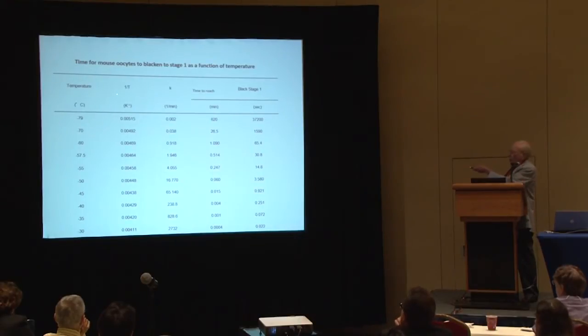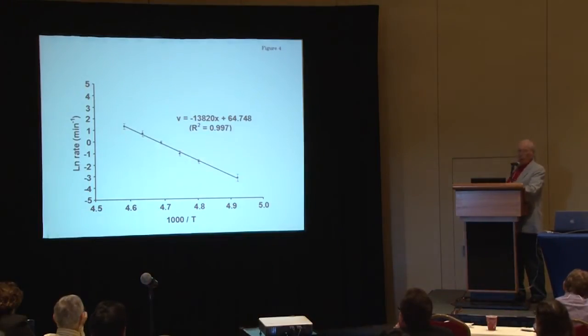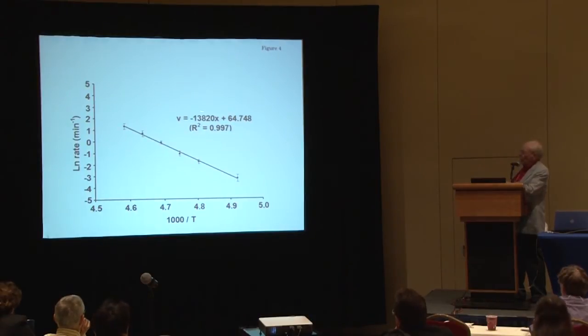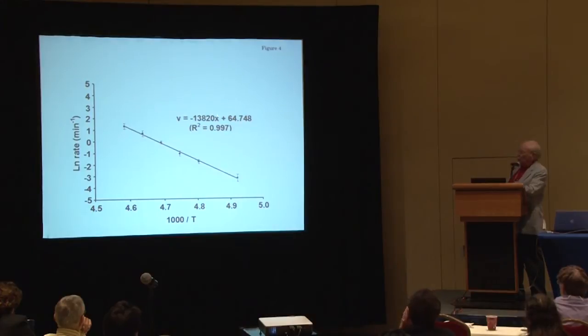The data from these experiments permit one to create an Arrhenius plot — a plot of the logarithm of the rate against the reciprocal of the absolute temperature — and it's a surprisingly straight line. The slope gives a measure of the activation energy for the process. The activation energy for this recrystallization is a very high value, about 27.5 kilocalories per mole. Interestingly, Kingery had previously published a paper where he took two spheres of ice, put them together, and measured the rate at which the neck filled in between the two spheres — and he came up with the identical figure of 27.5 kilocalories per mole.